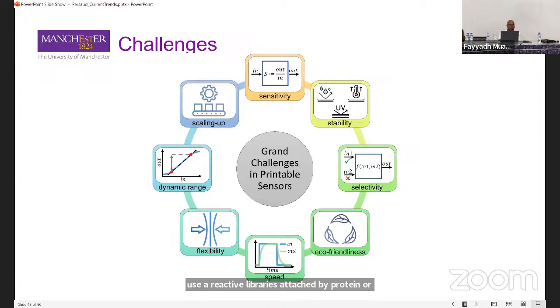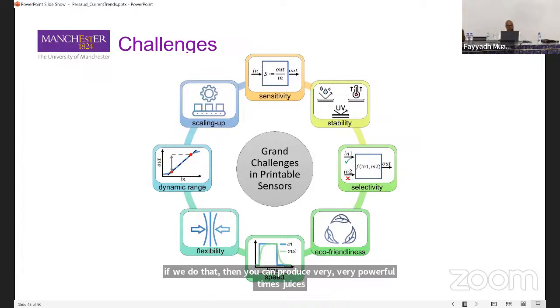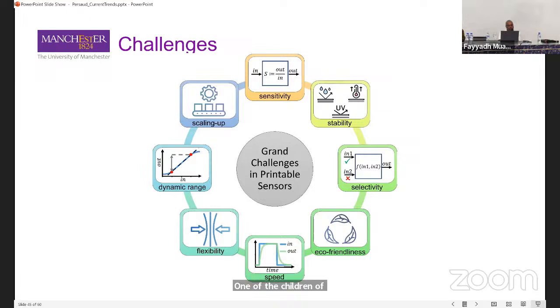And if you do that, then you can produce a very powerful transducer, very stable. One advantage of using diamond is part of mass transducers, like quartz crystal microbalances and surface acoustic wave devices. It's got a very high Q factor. So when you look at the frequency of resonance of the device, it becomes very, very sharp. And that means you have very high sensitivity.